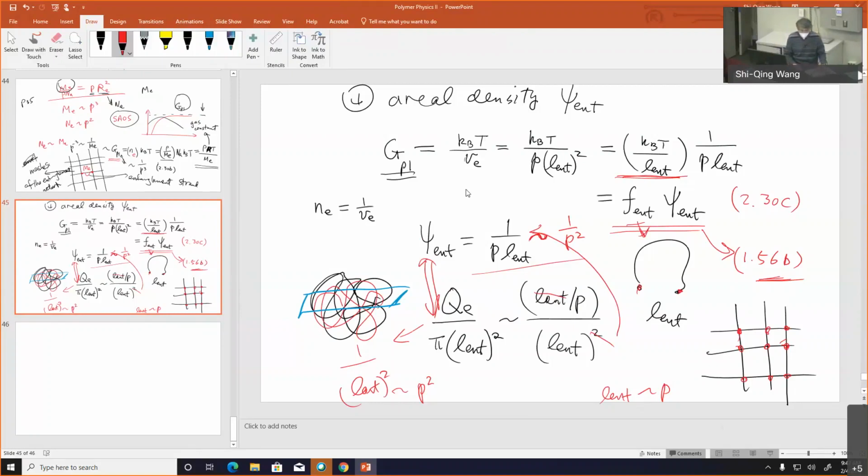I know in the outline we're supposed to talk about a case where this entropic elasticity concept, that you are limiting the number of configurations it can sample. Because if the chain ends are free, there are many more configurations they can find themselves in at different times. But now you're just holding them there, you're limiting the amount of entropy there is. And that's not favorable, so you pay a price by having to have a force there.